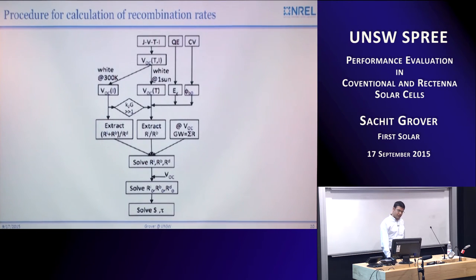So, to give you a summary of how the technique works, here's a chart showing we're starting with temperature and intensity dependence of the JV measurement, extract the VOC and VOC at one sun versus temperature, and you take a fixed temperature and VOC as a function of intensity, and perform the mathematics that I've already gone through, combined with band gap values, perhaps from quantum efficiency, and the interface inversion from CV built-in voltage, and you can essentially filter down to different levels and even solve for the lifetime and surface recombination velocity.